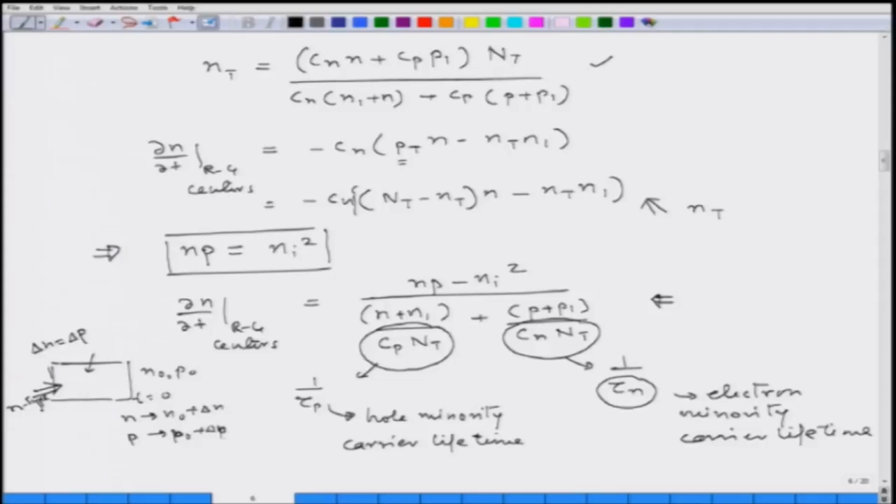So, when I have increased the electron and hole concentration in an N type material, the excess electrons do not change the concentration of the electrons which are already in the material, but the excess holes that I have put in change the minority carrier concentration to p naught plus delta P. If I leave it after increasing this carrier concentration, with time it would eventually relax back to p naught, to its equilibrium carrier concentration, with the lifetime of tau p.